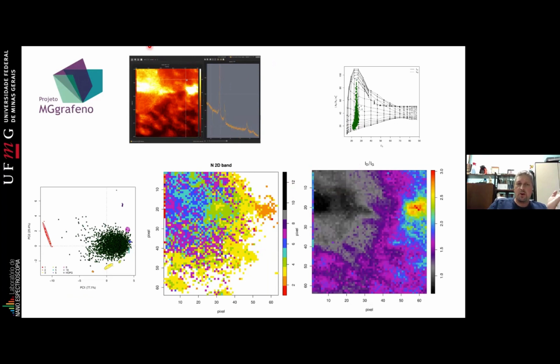The size of the laser spot in a conventional system is about 3 times this image here, but we have a lot of information about the local defects and the number of layers. We see there are many different numbers of layers inside 150 nanometers. Here we have a small number of layers, and there a large number of layers. We see that we have more defects where we have a low number of layers. This is correlated somehow. We are doing all these developments, and now we have some chemistry involved so we can make local analysis of our flakes. This is under development, and soon people will see how this technique can resolve a lot of problems, or at least raise some questions.